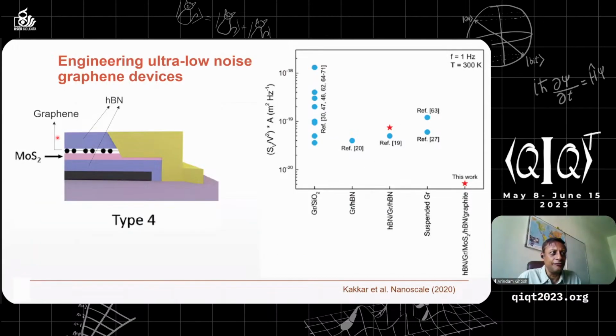Right. So it depends on which material you're talking about. As far as noise is concerned, we have looked into two classes of systems, semiconducting and two-dimensional materials-based systems, for many years. What we understand is that dark current is the main source of noise. If you have a metallic platform like a single layer graphene as a platform for optical detection, your dark current is very high. As a result, you will get 1/f noise, you will get shot noise, and they will create trouble. So you need to reduce the dark current, which is why we used bilayer graphene and reduced the dark current.